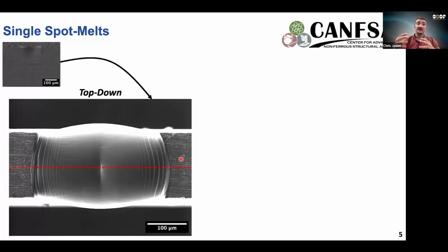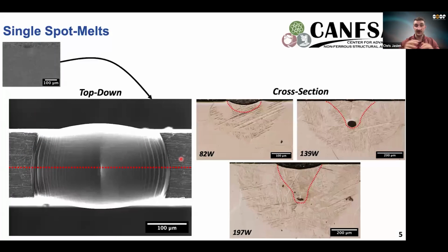And so when we want to look at this microstructurally, at the cross section, where it might be a little bit more representative of what's going on, we sectioned the material and looked at it at the cross section. And so here is optical microscopy of spot melts for 3 different power conditions denoted in the bottom left of each image. And the material that was actually melted, what we'd call the melt pool, is denoted with this red outline.